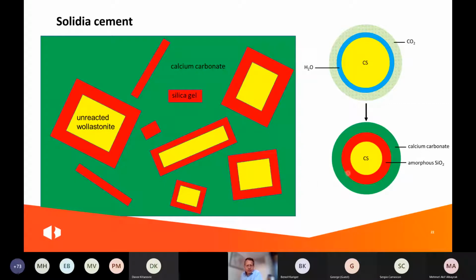Now here you have this process. You have here your cement grain, the wollastonite, water as a medium, and then the CO2. And here you have the reaction product, and here you can see the microstructure of Solidia cement: remains of the cement grain, silica gel, embedded in calcium carbonate.